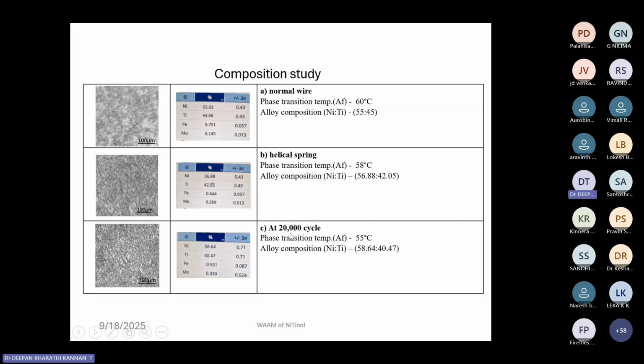And after 20,000 cycles, they were able to see that there are still changes in the chemical composition of the nickel and titanium. As a result, the phase transformation temperature is also getting changed. So this is the actual challenge that we have with respect to nitinol wire.